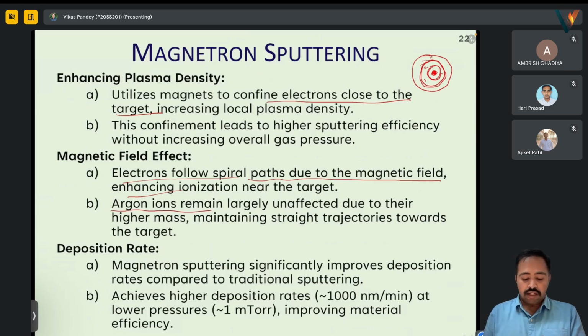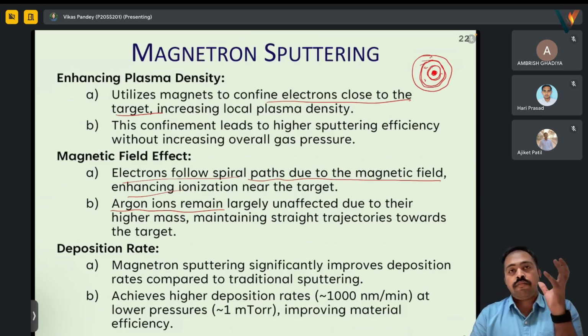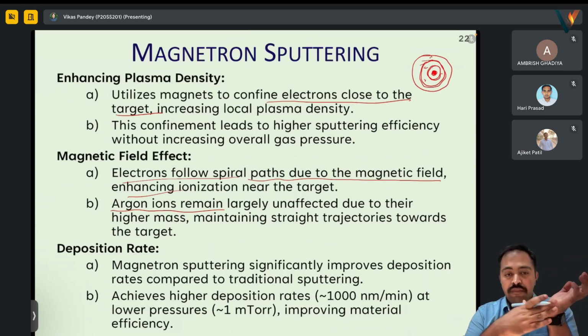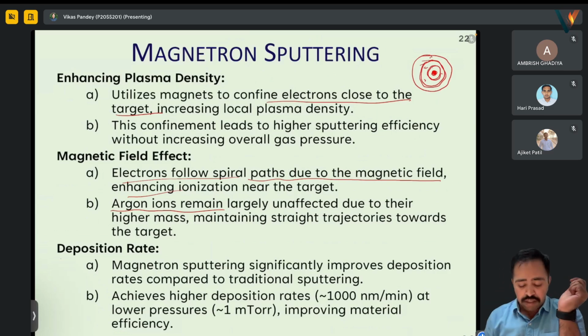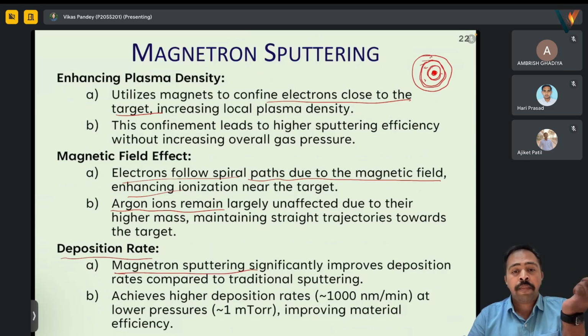as well as argon ions remain largely unaffected due to their heavy mass, and as such, though the plasma density increases, their path is not affected. As such the deposition rate is highly enhanced in case of magnetron sputtering, even around 1000 nanometer per minute. Okay, so it can be very fast, that is 1 micron per minute deposition can even be done using magnetron sputtering.